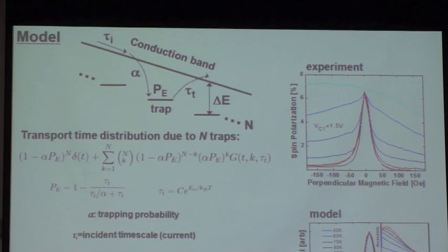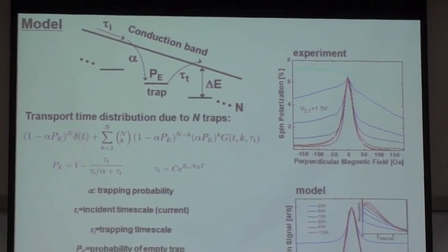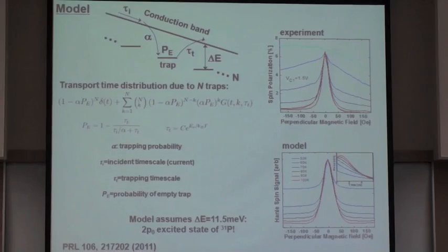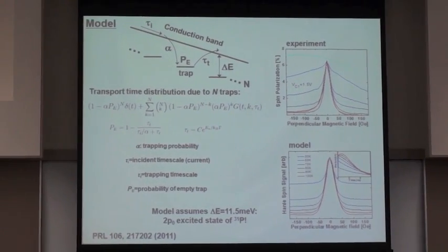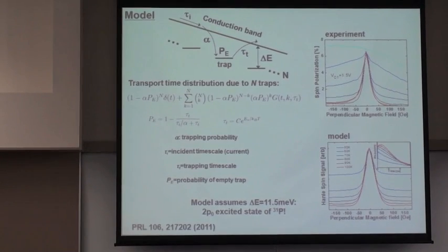And what we measure on the other side of the detector, of course, are electrons which are passing straight through and not affected by this trapping and re-emission process, but also electrons which are trapped once, electrons which were trapped twice, and which have a distribution of trapping times, in other words, dwell times in this trap. And all the while they have maintained their spin polarization, and they've also been maintaining the precession under the influence of the magnetic field the whole time. And this is essentially giving us a means to clock or to time the transport distribution.